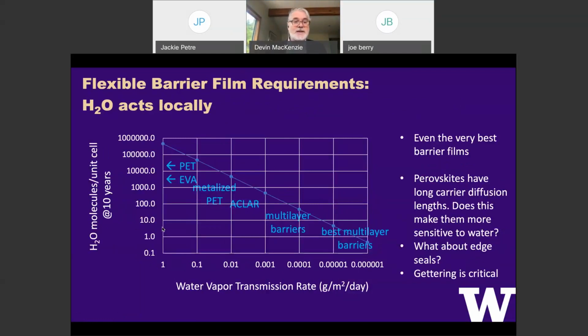in the sense that we care about each unit cell of the perovskite, say we match one water molecule per unit cell of perovskite. Maybe that's the very optimistic degradation limit, like we'll have perovskite until the stuff literally dissolves. We'll have a solar cell until it dissolves. The reality is probably somewhere in between these two extremes. But even in that case, we're still getting near one H2O molecule per unit cell in 10 years. Literally, the film will be, unless we do something different, entirely saturated with the best flexible barrier films.